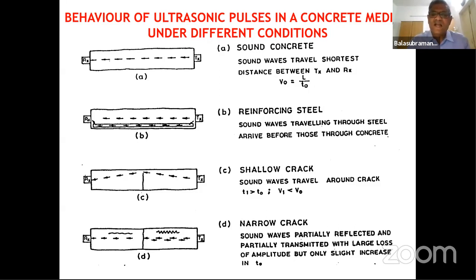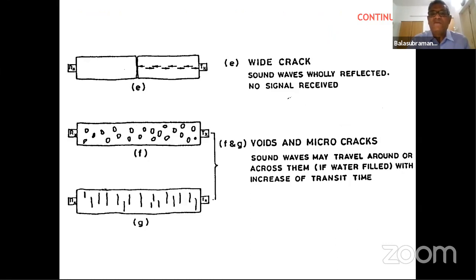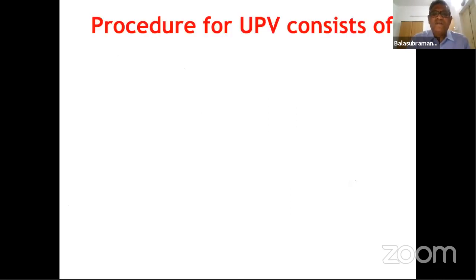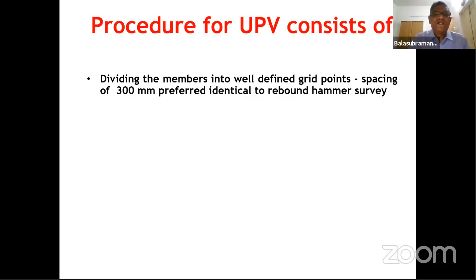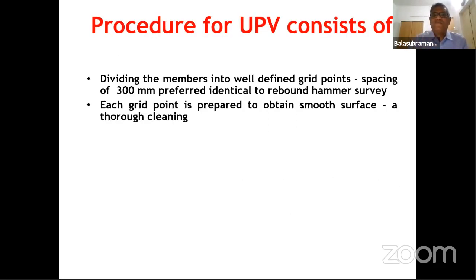And when you have cracks, naturally the sound waves have to travel through the cracks, so the time taken is more. A narrow crack will sometimes be partially reflected. A wide crack will definitely be reflected, and you will get unstable readings or no signal will be received. And then with voids and micro cracks, sometimes you may get a very low value or an unstable reading. So the general procedure is we have to divide the member into well-defined grid points.